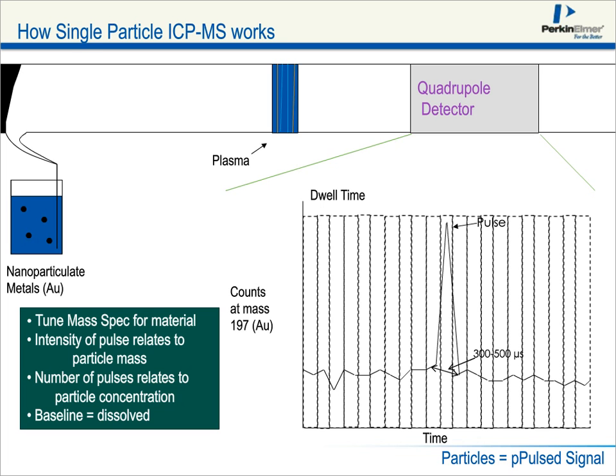And the intensity of the pulse, because now we are acquiring all the ions in that pulse, that amount of ions is related to the particle mass. And of course, the background, which is the straight line on which we have the pulse that comes on top of it, is really the baseline. So it is equal to the ionic fraction or the dissolved fraction that is in that sample itself.